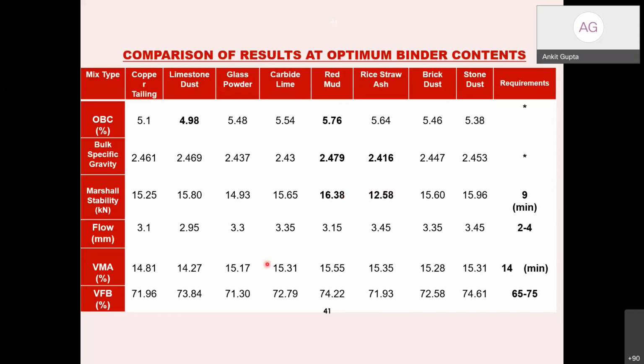Flow values are again in the range of 2 to 4. VMA should be minimum 14%. All are having values more than 14%. Voids filled with bitumen should be between 65 to 75, and all are in the range. This slide can slightly conclude that we can use all these waste fillers in our pavement industry.